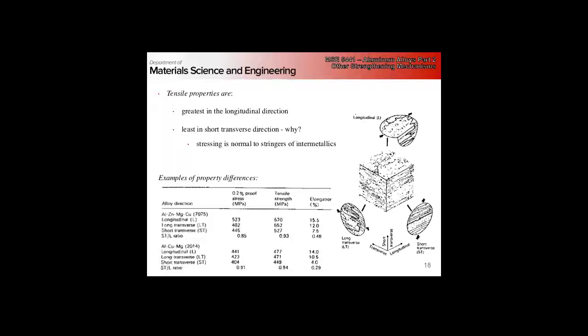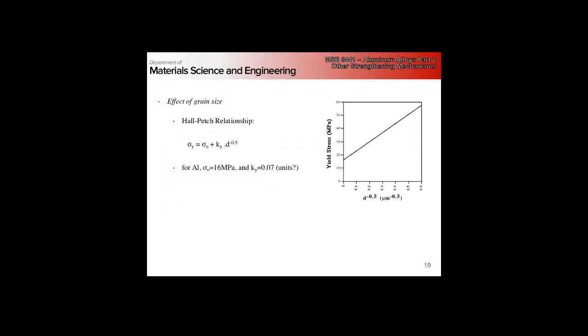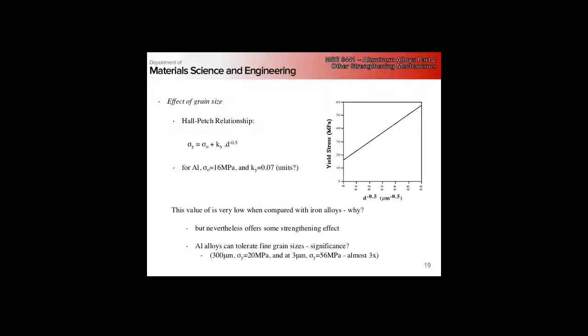You want high strength, high ductility, high toughness. But strength and ductility, and strength and toughness, are usually inversely correlated with each other. Okay, so the other property that we want to consider is the effect of grain size. And I had mentioned that the Hall-Petch coefficient for FCC metals is very low compared to BCC and HCP. Aluminum is particularly low, or 2 orders of magnitude less than good steel alloys for the Hall-Petch effect, right?